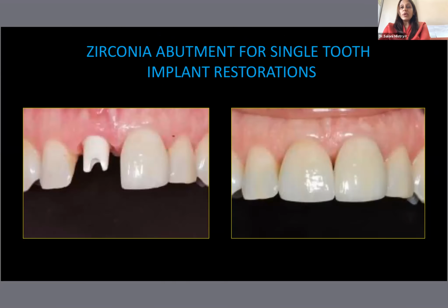Obviously, with implants in the anterior aesthetic zone, you want an abutment which is probably a titanium base or a zirconia abutment. If it's a zirconia, then you would probably use a lithium disilicate crown. But if it's a titanium, then there are various other situations where you can have a tie base, you can have a titanium abutment, and then you have to mask that underlying metal, and the bonding systems also have to be very, very carefully used, wherein with any form of zirconia and titanium base, and when you are bonding a lithium disilicate, it's very essential.